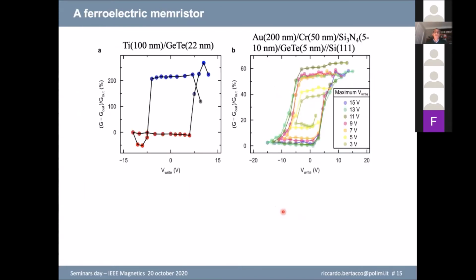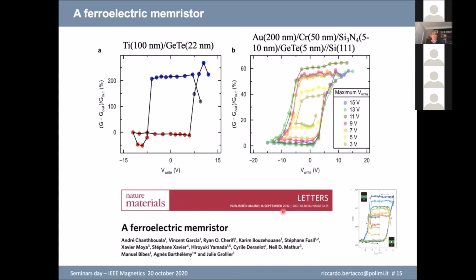But this is something connected to the electrical behavior, which is also interesting because in principle you can also use it as a sort of memristive device. But for the present talk, the interesting story is that if you can now control the ferroelectric state just by looking at the impedance and the IV curve of your gate electrode, this means you can have good control of the ferroelectric state in a device, and also follow what is happening when you perform a spin to charge conversion measurement. And okay, just to say that we have something similar to a ferroelectric memristor, obviously.